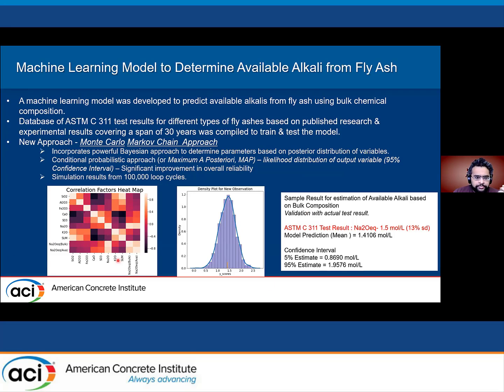As we see from this figure on the left, this is essentially showing us that the available alkali cannot be determined from just any one or two parameters, or just on the bulk composition, bulk Na2O or bulk SiO2. Almost the entire composition plays a certain amount of role in the overall contribution of the available alkalis from the fly ash. And this is an important point to consider.